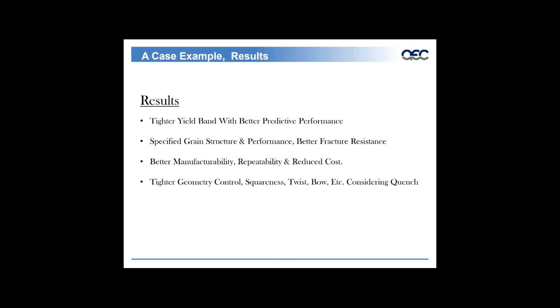So the results of those modifications: a tighter yield band was able to provide a better predictive performance. Specified grain structure and performance yielded better fracture resistance, better manufacturability, repeatability, and reduced cost. As a result of sectional controls and understanding of the twist and bow, tighter geometry control, squareness, twist, bow, etc., considering the quench that was utilized for this specific alloy. The understanding of post-weld locations and surface conditions and seam weld were taken into account for downstream operations. And engineered weld locations relative to high stress conditions were taken into account.